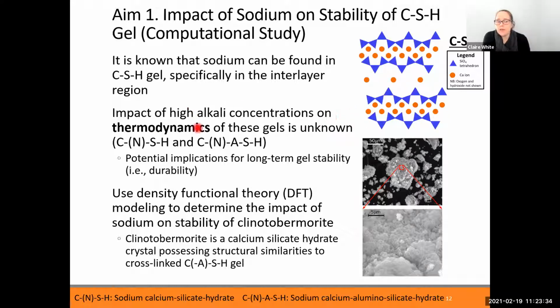But what we don't know is the impact of the high alkali concentrations on the stability of these phases. So if we're looking at calcium silicate hydrate gel with sodium in it, or CASH gel, where aluminium's in the gel as well, and then there's sodium in it, what impact does this sodium have on the propensity for the gel to dissolve, say, in certain environments, or react with carbon dioxide, which these phases do react with? So this information has potential implications for long-term performance of the concrete, specifically regarding the gel stability.